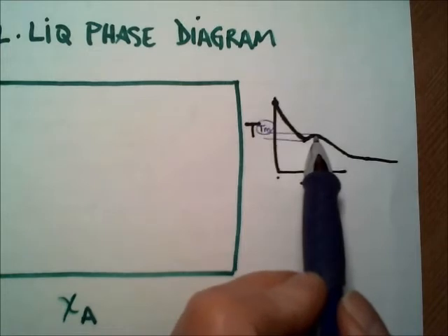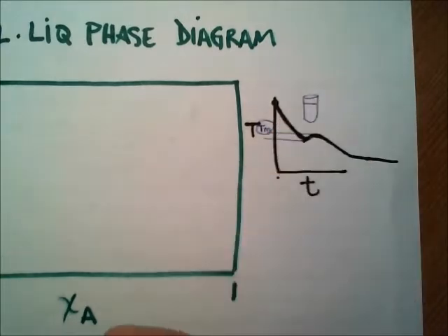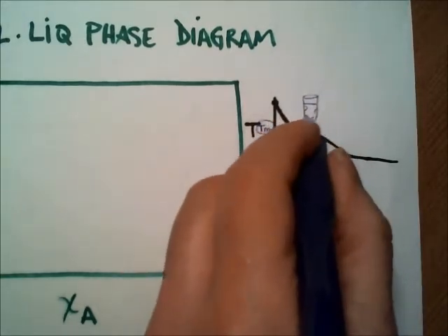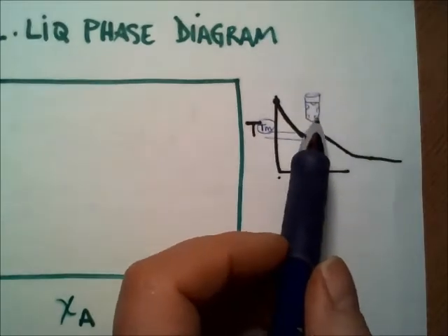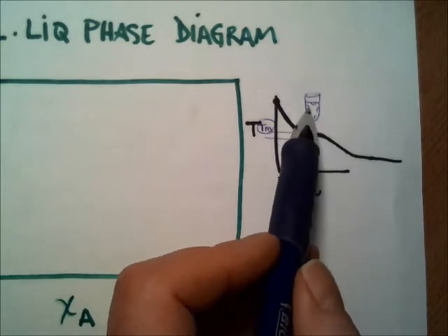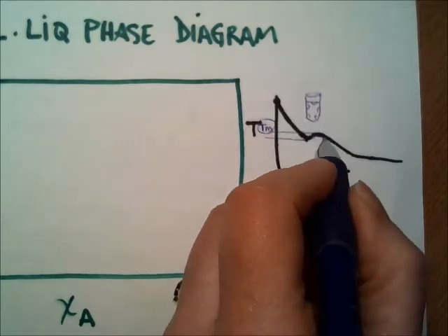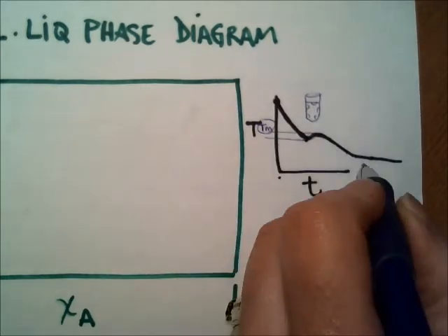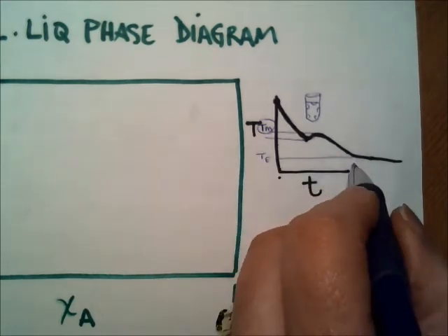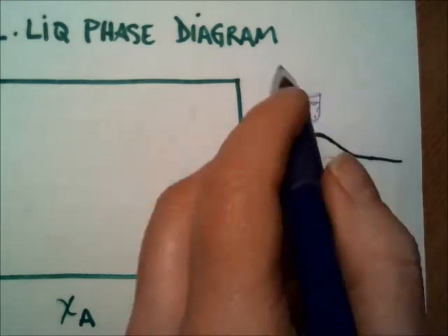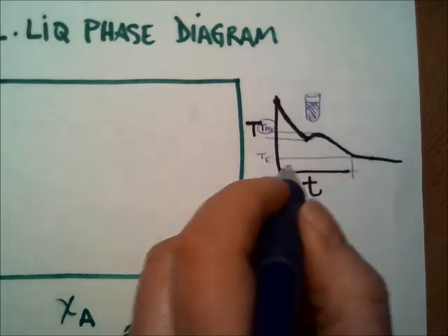What you see at this point in your test tube is that you probably had your melt liquid, and then maybe some crystals growing on the lower free energy surfaces like the air-liquid interface or meniscus and the sides of the glass. And so you have that within a slush, and then with continued cooling you hit what's called the eutectic temperature, and at that point everything solidified, and it just went solid on you.